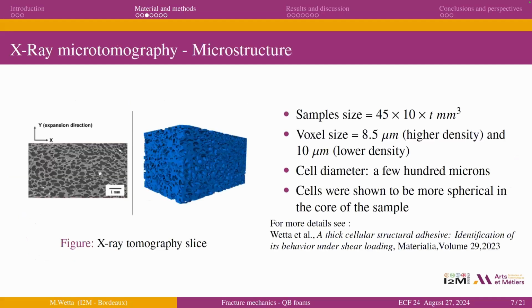So the microstructure has, of course, been characterized because it's quite complex. The microstructure is finally a little bit large because we have cells of about a few hundred microns. So it is possible to use laboratory X-ray tomography, and we can have good information about the microstructure and the cell size and orientation.